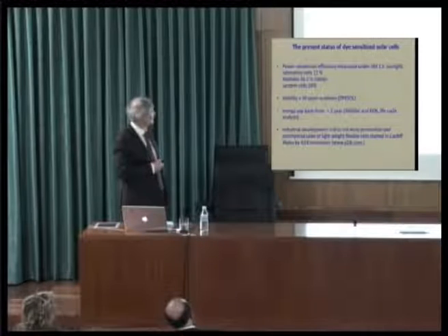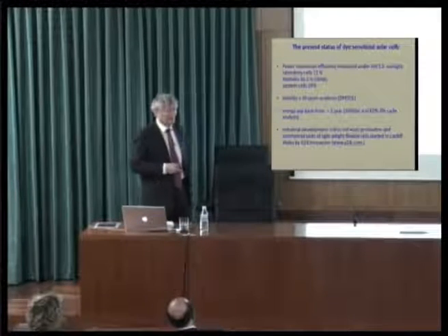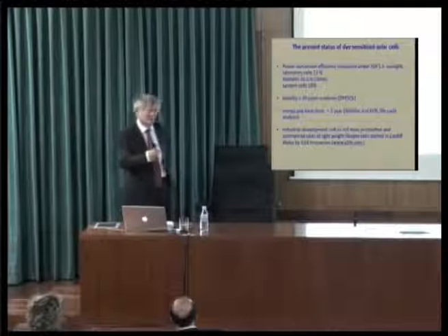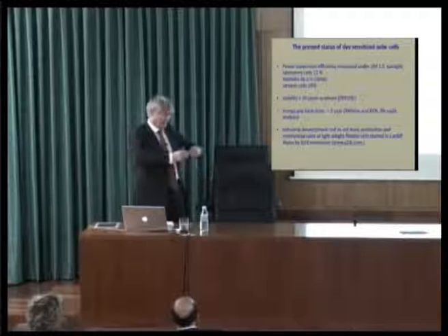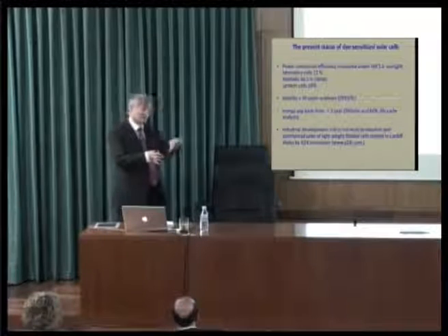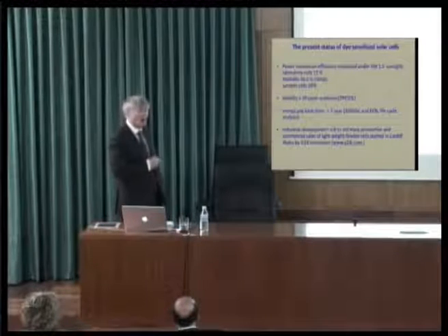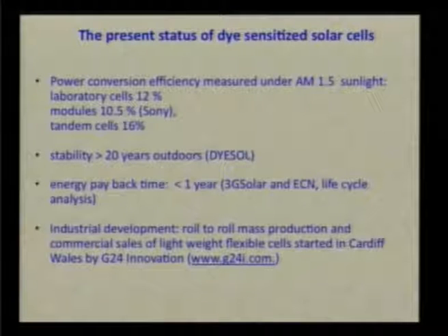Some people think that's incredible. You can't get that, you must lose more. Well, no. This technology is very easily scalable because we print our films by screen printing, and it's forgiving. The only loss you have really is with the fill factor of the cell, because if your device size increases, you might get some IR loss. And also, if you use a collector, then your active area will become smaller. But these are aperture area efficiencies, not active area, total area efficiencies.